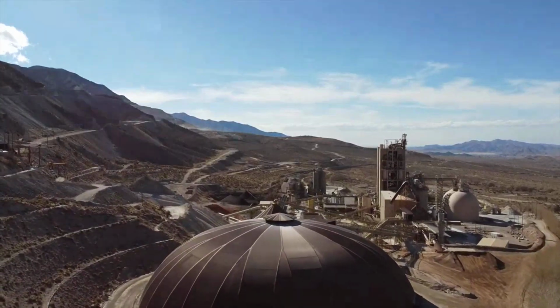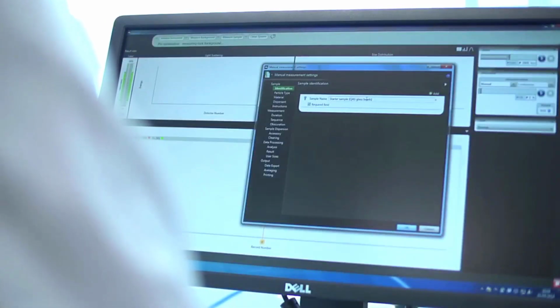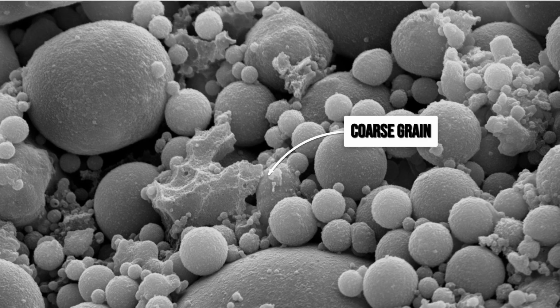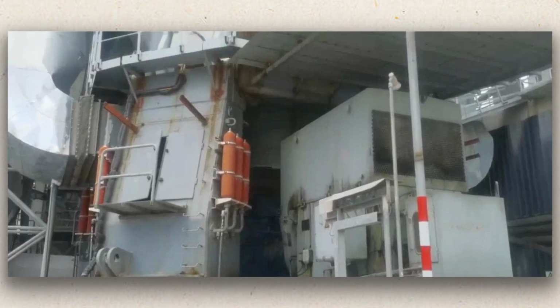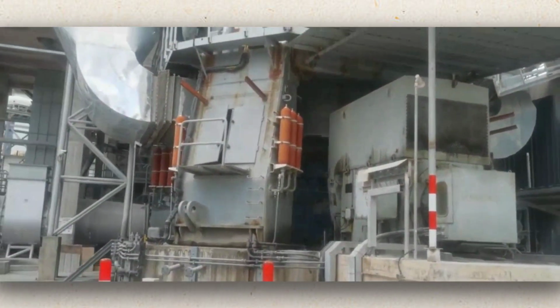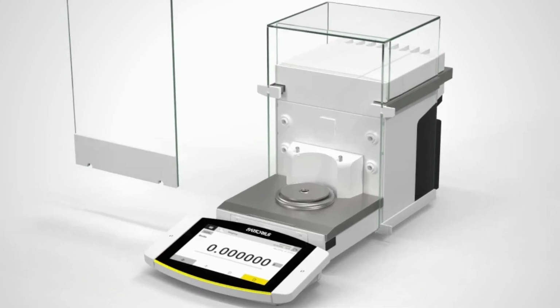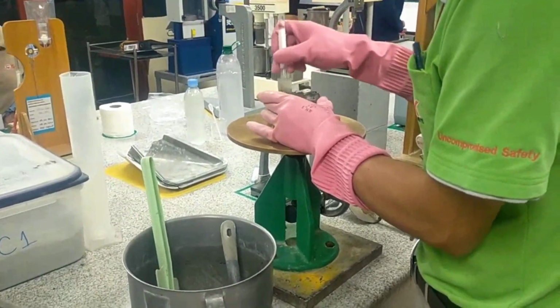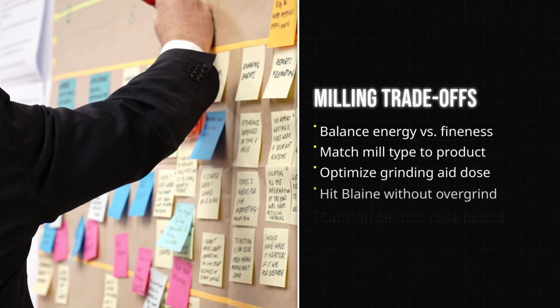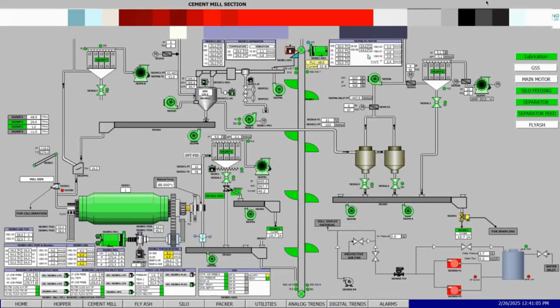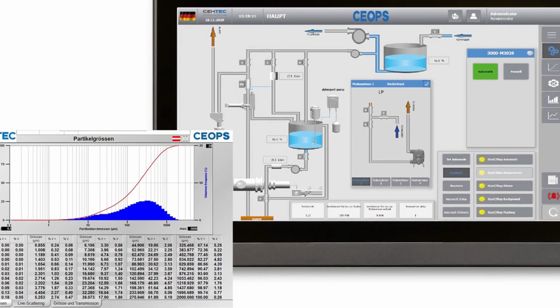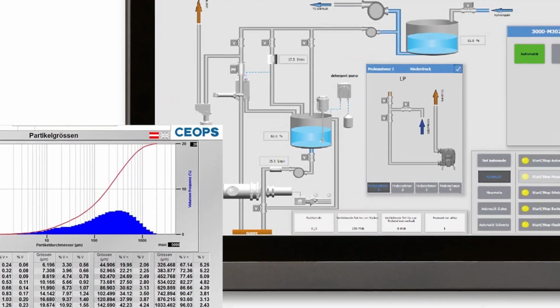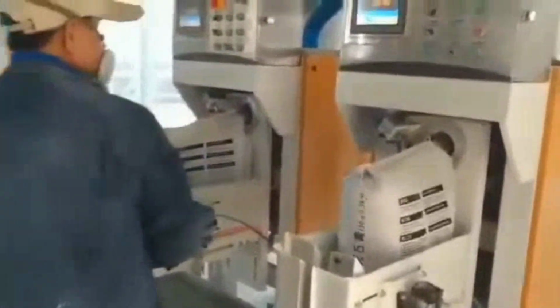The impact goes beyond energy. Particle size distribution tightens, with more grains in the optimal 3 to 10 micrometer range and fewer coarse or ultra-fine outliers. Early strength improves and flowability rises, allowing mills to run faster without risking blockages or quality slips. Still, the balance is delicate. Overdosing can raise water demand or blunt long-term strength. In the end, the right combination of mill type, grinding aid, and Blaine target is a moving target, recalibrated with every shift in feed or product specification. This is particle engineering in real time, with every adjustment logged and every outcome measured in throughput, cost, and the steady filling of bags on the line.